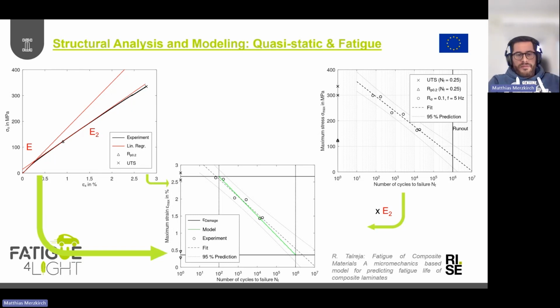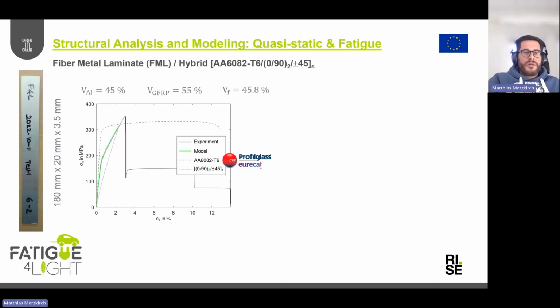Now we're coming from the glass fiber reinforced composite and adding metallic layers. In this case, we are adding a hardenable aluminum alloy, an aluminum-magnesium-silicon alloy in the heat treatment state T6. This is what we call a hybrid, or a fiber metal laminate, as shown here. Here we see the specimen in a tension test, and we compare that to the T6 aluminum alloy and also the inlay of glass fiber reinforced composite.